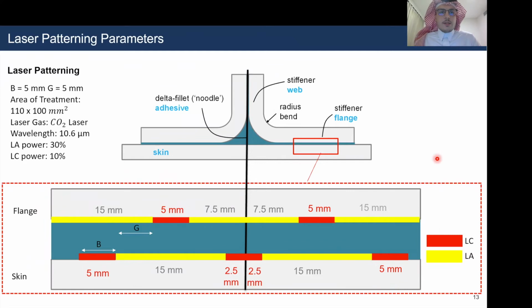So for the laser patterning, the parameters, taken from the name B5G5, were taken from a previous study, which concluded that these parameters produced the best toughness in the mode 2 end notch flexural test. So it was taken by leaving a gap of 5 millimeters and taking a width of LC of 5 millimeters.